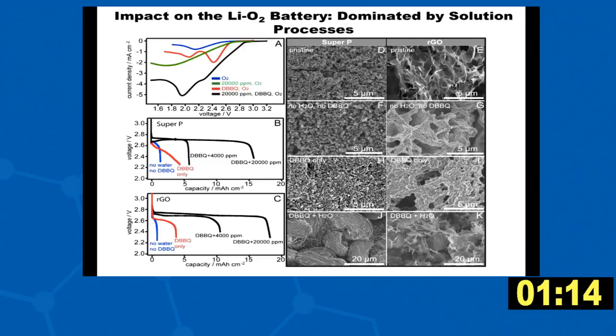And so this is now a comparison of Super P and RGO electrodes, and this is the discharge capacity with no water. Then we add DBBQ, and you can see it improves significantly. If we move to a graphene electrode, we get a much better voltage versus capacity. We then add water, and you can see the capacity increases dramatically. And so you can see this more clearly if you're not an electrochemist.